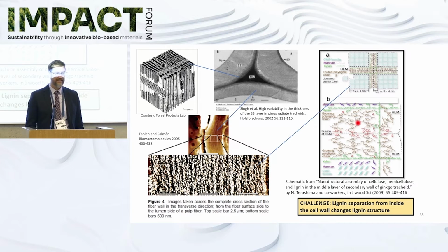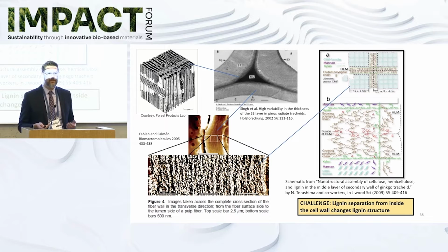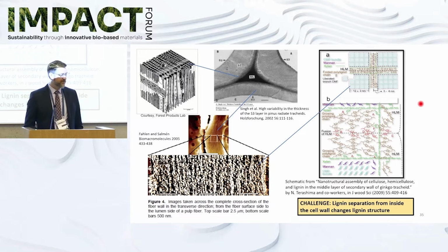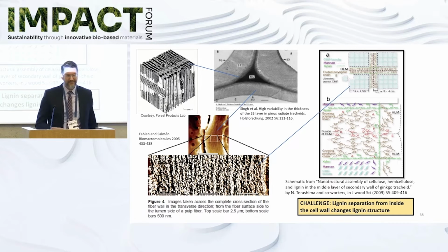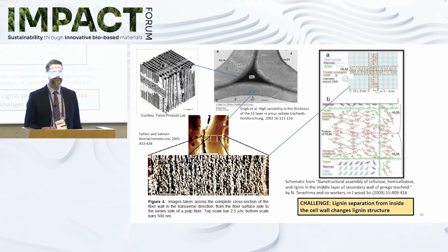If you look a little closely at that, you see lignin is this aromatic polymer. The pulp and paper industry does a great job of removing the lignin from the cell wall. The problem is that when you begin to remove the lignin, and it's actually pretty difficult to do this, you end up changing the structure as you're extracting it out. That's one of the challenges with lignin separation: you end up modifying that structure. And depending upon the methods that you're using, the degree of change can be significant.